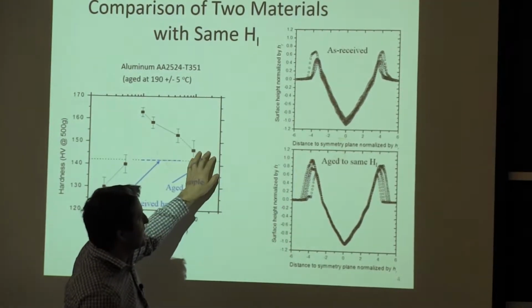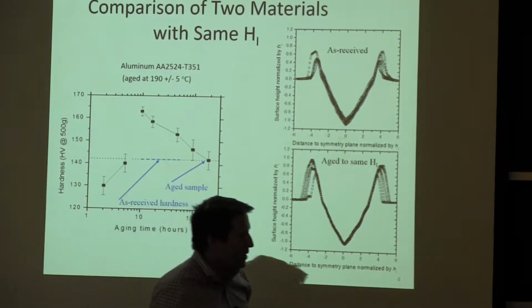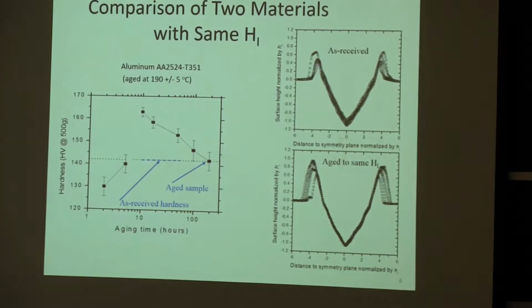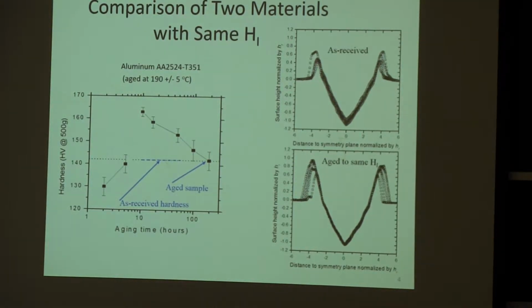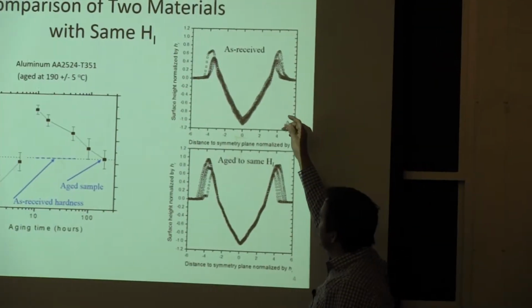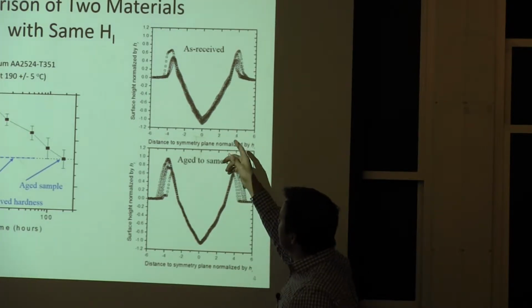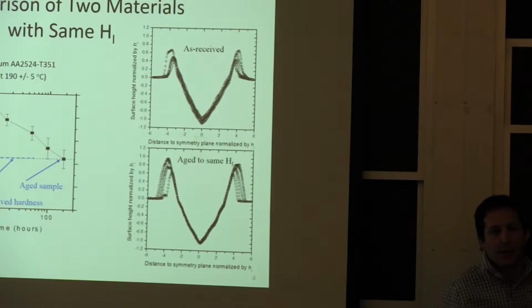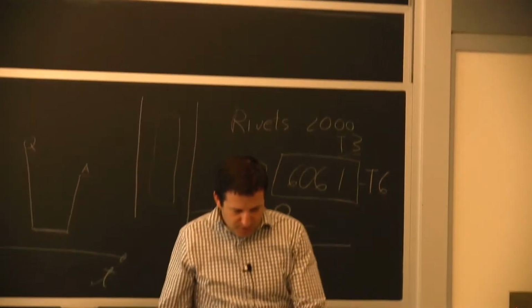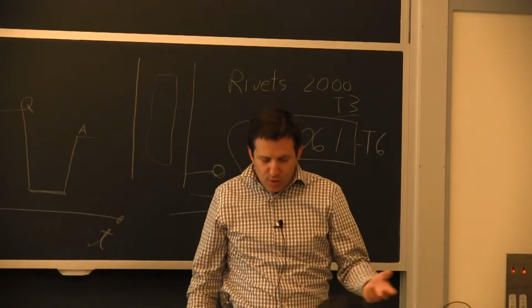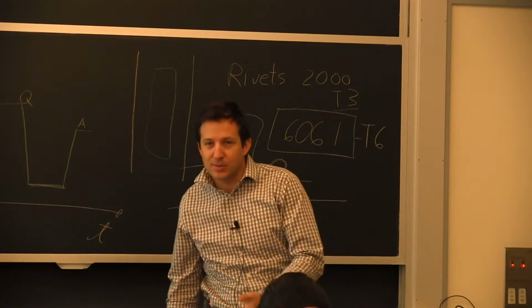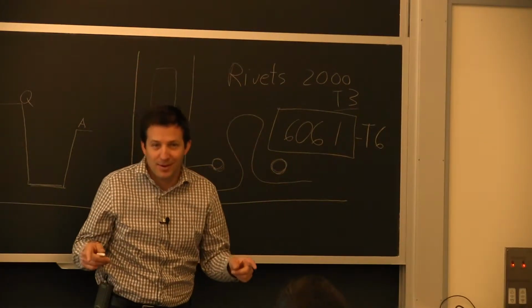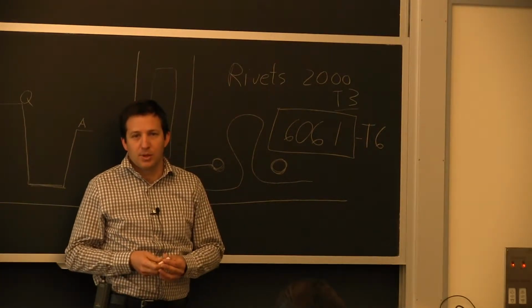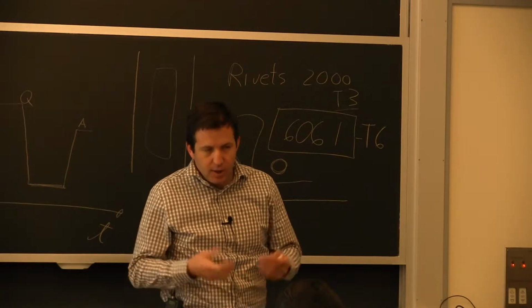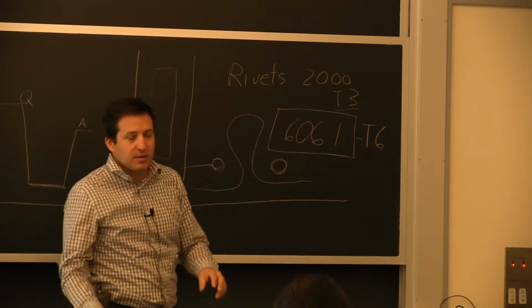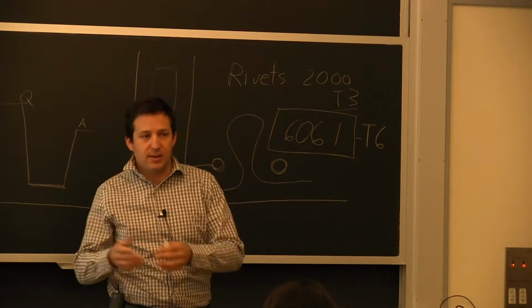So again, this is bigger precipitate. The material doesn't consolidate as much because the dislocations start going right through the precipitates as opposed to forming these loops here and essentially multiplying the dislocations. If you have multiplication of dislocations, everything hardens, you distribute more of the strain, and the material doesn't extrude as much to the surface. Part of this experiment was really to show you can gain more information if you're doing a scratch as opposed to a hardness test, because when I went to the lab and ran the hardness test, I got the same number, but when I ran this test, I saw a bigger difference between them. So it's a test that's very sensitive to hardening of the material, which relates to whether the precipitates are slightly smaller than the maximum hardness or slightly bigger.